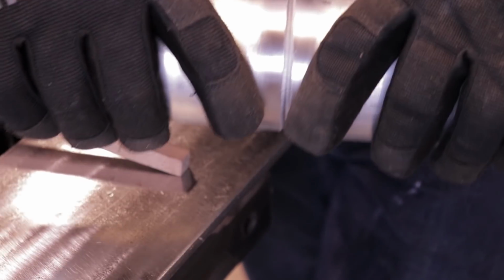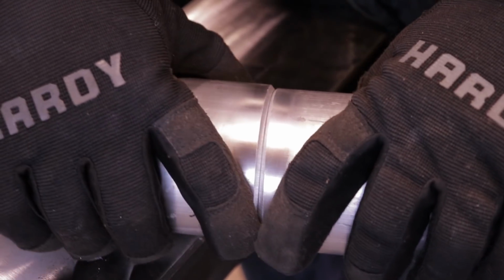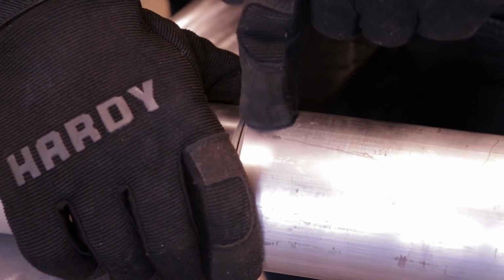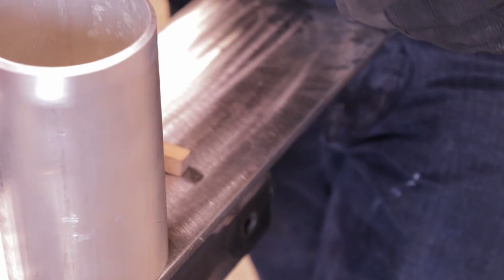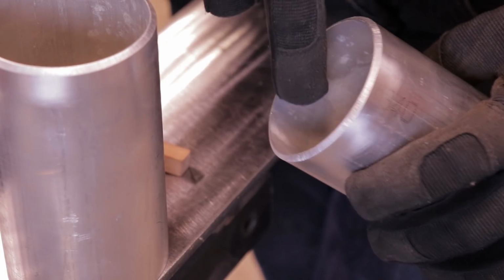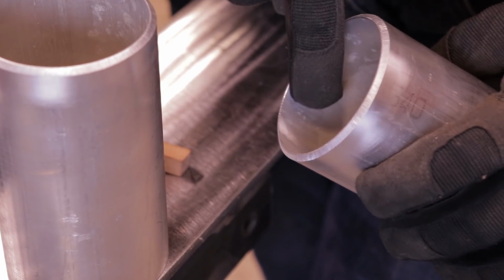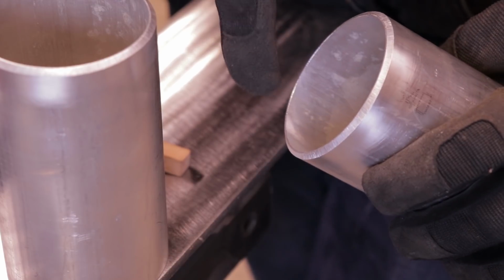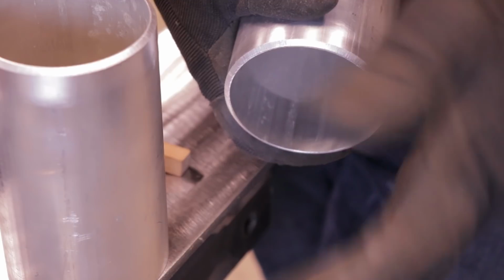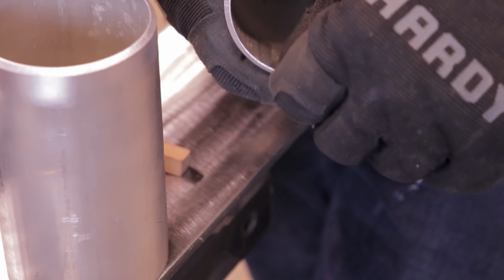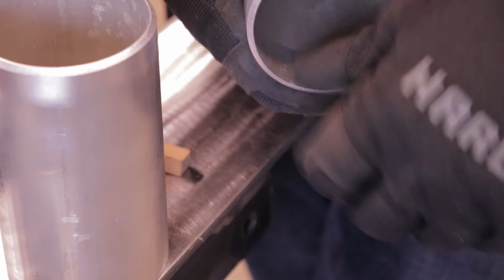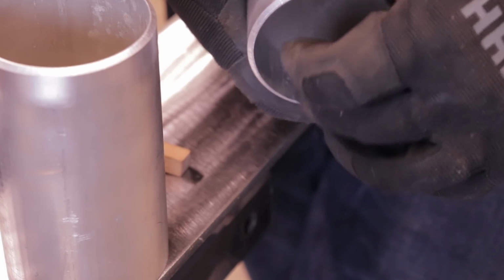Basically, when you're welding two parts that are put together and it penetrates through, it's just raising the oxide layer, and the puddle is pushing up, and that oxide layer is staying on top of it, because there's no cleaning action from the torch inside to remove it, so it's just pushing it up. That's why it'll look a little funky, but it's not sucking in any atmosphere from the backside.